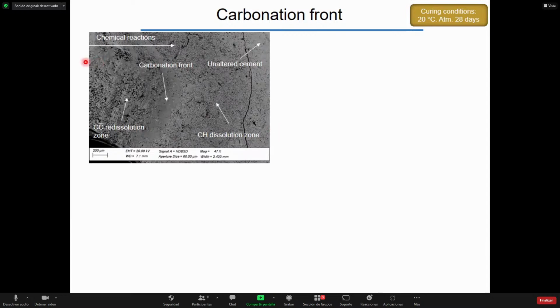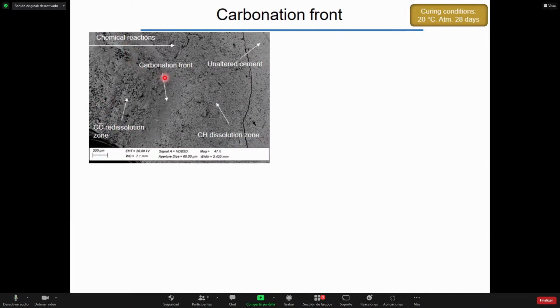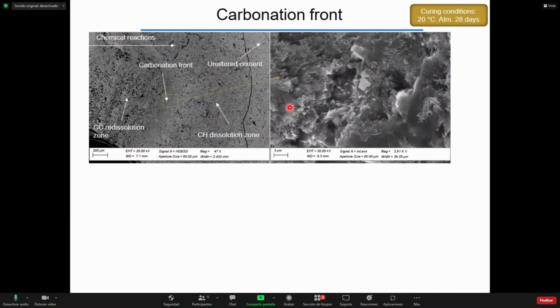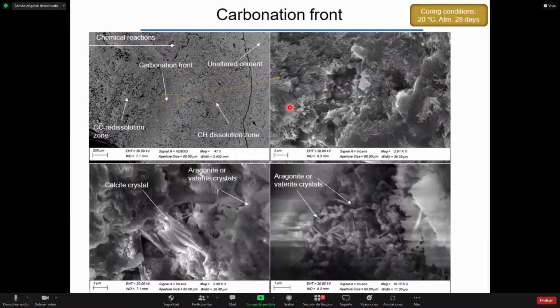For example, in this case, if the chemical reaction goes in this way, the zone near the exposed edge will have a calcium redissolution zone right next to the carbonation front and next to the Portlandite dissolution zone, and the unaltered core cement. The carbonation front is characterized by high crystallinity, where calcite crystals start to precipitate, as well as aragonite and vaterite crystals, which are polymorphs of calcium carbonate.